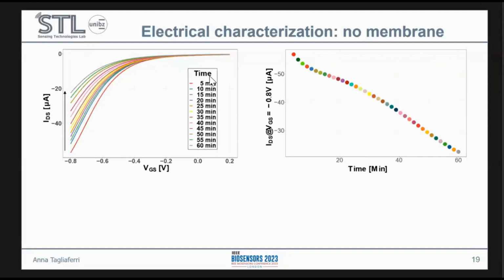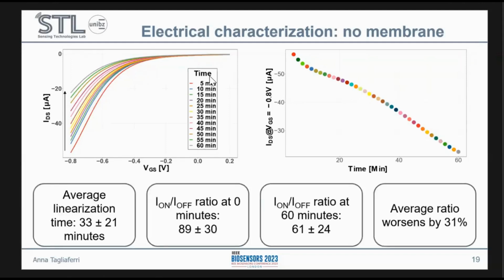We then tried to perform a linear fitting on this plot here to see how long it would take for our devices to reach a linear current over time. What we considered good linearity is when the R squared was higher than 0.98. So on average, we obtained a linearization time of 33 minutes.